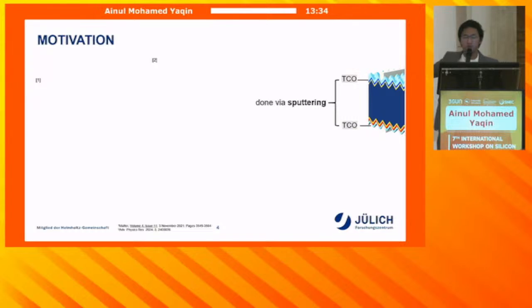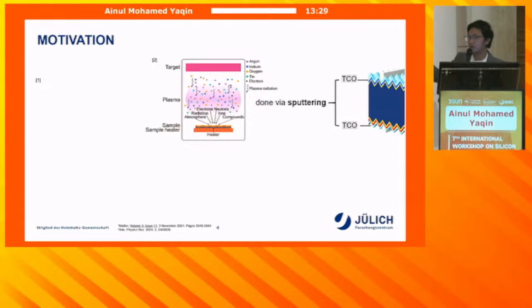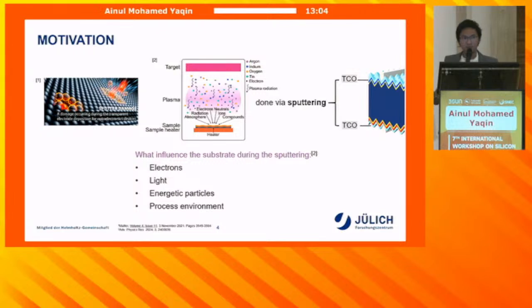So the TCO layer is usually deposited by a method called sputtering. In sputtering, you have the target material, let's say indium tin oxide, and a high energy plasma bombards the target, ejecting atoms or particles that travel through the chamber and condense on the substrate, forming the thin film deposition. But it is very well known in the community that the sputtering process can damage your substrate.